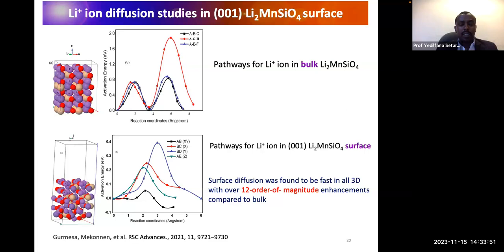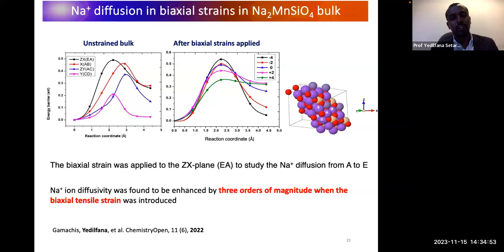Next, we calculate the nudged elastic band calculation for the surface. For the bulk, we have seen it already before. The top one is for the bulk. And for the surface, we tried 4 lithium diffusion channels, and we found all of them below 0.4 electronvolt, which is below 0.5. As I've told you before, this is acceptable and it definitely improves the ion mobility. It makes it very easy, and very fast ion diffusion can take place. So if you compare the bulk and the surface, diffusion was found to be fast and improves the conductivity, with an over 12 orders of magnitude enhancement obtained in the surface compared to the bulk, which is a very big improvement.